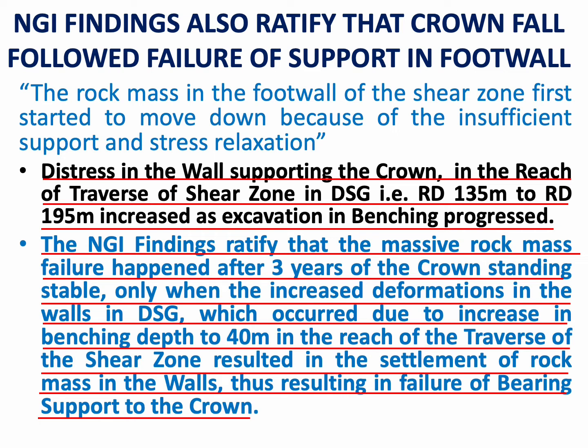Now, as the excavation in the benching was progressing, this particular reach of RD 135 meter to RD 195 meter in the distress wall, which was supporting the crown, was seeing movement in the footwall. The NGI findings ratify that the massive rock mass failure happened after 3 years of the crown standing stable, only when the increased deformations in the walls in DSG, which occurred due to increase in the benching depth to 40 meter in the reach of the transverse of the shear zone, resulted in the settlement of rock mass in the walls, thus resulting in failure of the bearing support to the crown.